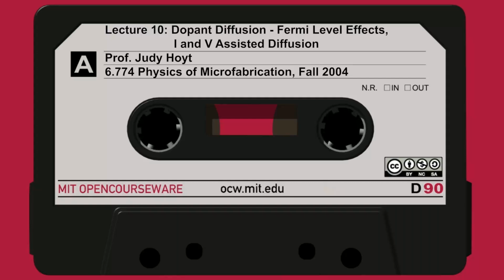There's this pair, and they move as a pair throughout the lattice. So how can that happen? Well, you can imagine this. Let's say this is my first time step. Here's a vacancy right here. Here's a dopant atom pictured in the light, and the silicon atoms are all the dark black. So this dopant here may exchange site with the vacancy, okay? The dopant moves to this vacancy site, the vacancy moves up there.